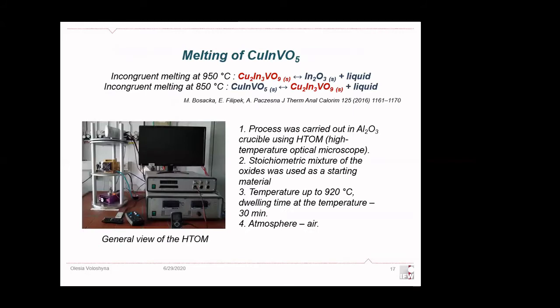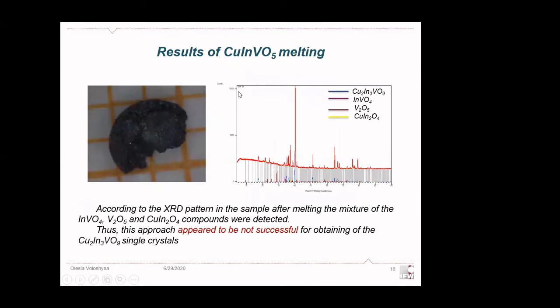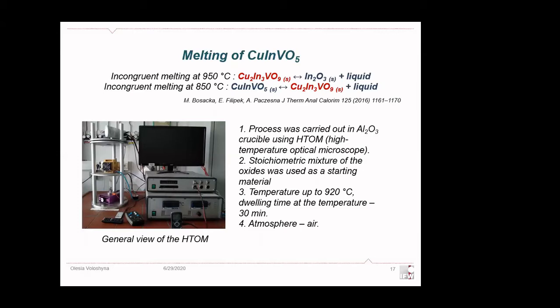And according to the ternary phase diagram between copper oxide, indium oxide, and vanadium oxide, we obtain in this system two different mixed vanadates with different stoichiometry: 115, and our goal compound 239. Interestingly, this copper vanadate with stoichiometry 115 melts incongruently too, but it melts at a lower temperature than our goal compound. And as a solid product of the melt, we have our goal compound 239. So the first approach for obtaining the goal compound was just melting of this compound with another